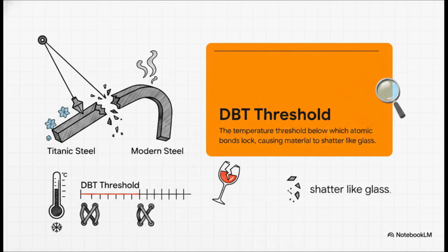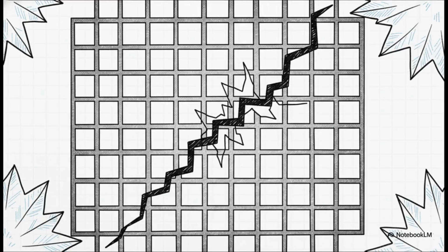This brings us to a crucial concept, the ductile to brittle transition, or DBT. This is the specific temperature threshold below which atomic bonds lock in place, causing a material to shatter like glass instead of yielding. Decades after the sinking, a forensic Charpy impact test swung a pendulum into chilled Titanic-era steel, proving it snapped instantly, while modern steel simply bent. The issue wasn't that the Titanic steel lacked raw strength. The issue was the rate of deformation at low temperatures. So the atoms literally froze in place.